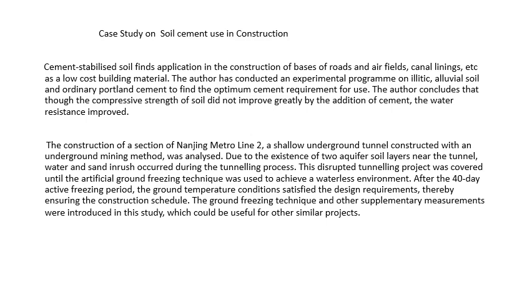Case Study on Soil Cement in Construction: Cement Stabilized Soil finds application in the construction of bases of roads and airfields, canal linings, etc., as a low cost building material. The author conducted an experimental program on Illitic Alluvial Soil and Ordinary Portland Cement to find the optimum cement requirement for use. The author concludes that although the compressive strength of soil did not improve greatly by the addition of cement, the water resistance improved.